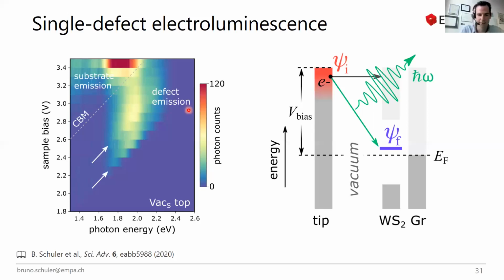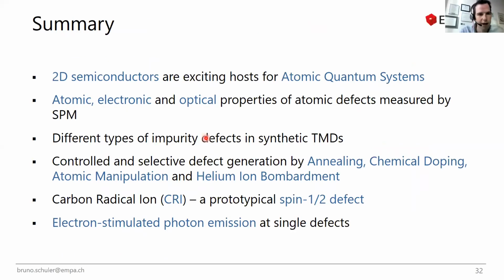So the question might arise, why is the defect not more narrow in terms of spectral bandwidth? And the reason is, again, because we have here a continuum of states. So not only can your electrons tunnel from your Fermi level, but also from more down here. So they tunnel with different probabilities, depending of course on your tunneling barrier, but again, also this photon density of states. And just in the spectral range here of the gold plasmon, we see a strong enhancement. So this is like a Purcell enhancement of your plasmon that is mainly localized at your tip. And this also helps to mediate the coupling from the near field to the far field where we actually detect these photons. So that's the summary of the talk already.